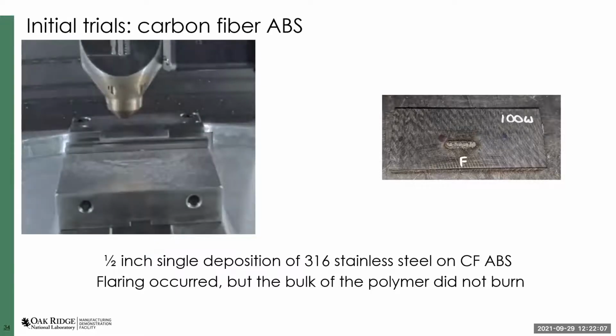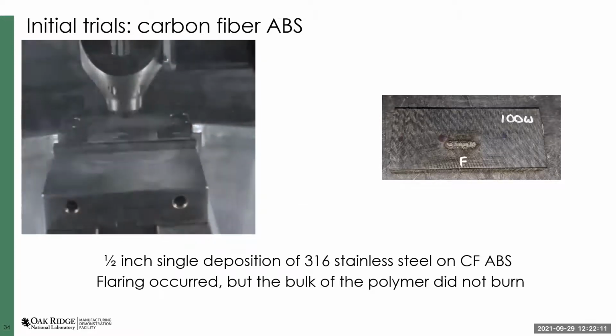This is actually the first one that I ran, which is a stainless steel pass at 100 watts on the system with carbon fiber ABS as a substrate. I'll just play that again. What we get is a lot of flaring and sparking, but we don't get any, I've been told to call them thermal excursions by the lab for safety purposes. So we don't see anything that sparks a lot of safety concern, although we do see more flaring than traditional metal on metal deposition. And you can see in this image that the substrate did survive with minimal geometric integrity loss, which is exciting. The bulk of it didn't burn and didn't melt.